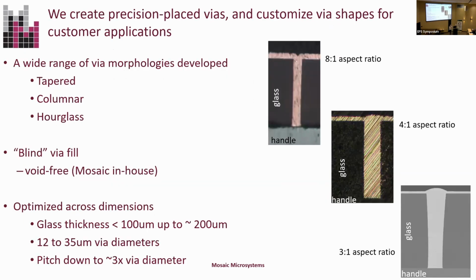So I mentioned that we create the TGVs. We've worked very hard on making sure that we understand how to create different shaped vias. In some cases, a tapered via is advantaged for our customers. And you can see at the bottom here, a 3:1 aspect ratio via that has been filled with copper. The overburden is still in position. So what you're seeing there is the silicon handle down below, the glass wafer, and copper fill.